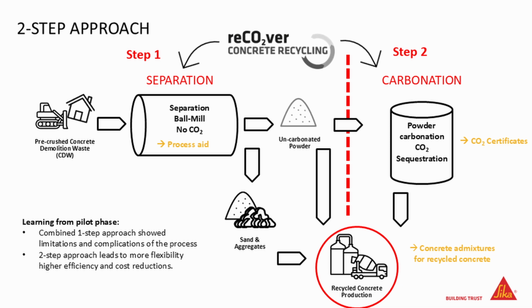So in step one, we get out sand and aggregate in quality comparable to primary material, and we get the uncarbonated powder. And then the question is what to do with that powder. One option for sure is to bring it to step two, to bring it in contact with CO2, to have the CO2 sequestration, because you have this powder, which is very fine, roughly a maximum size of 100-120 micrometers. So you have a lot of surface. When you put the CO2 there, it reacts immediately. The reaction time is roughly 15 minutes. So when you leave it half an hour in the reactor, you have it completely carbonated.